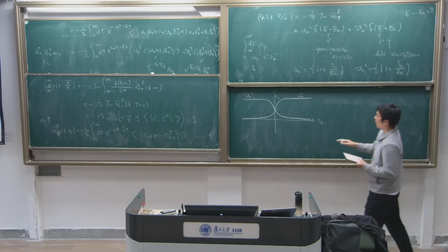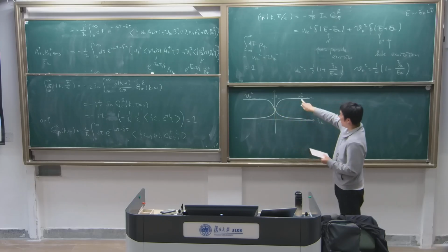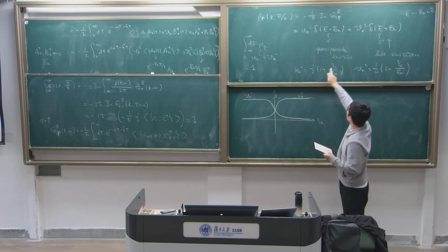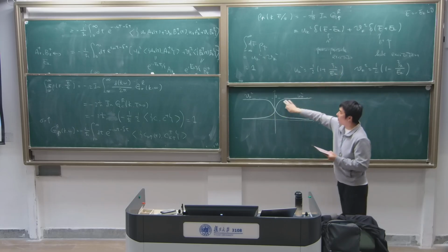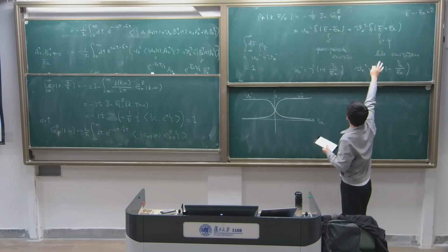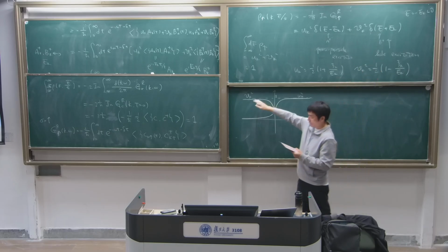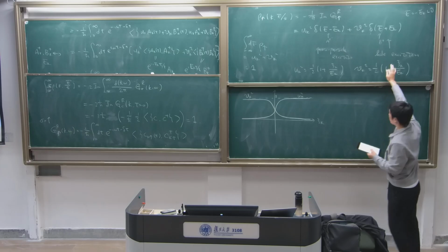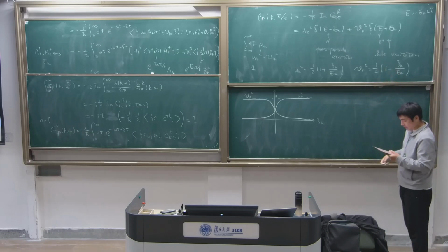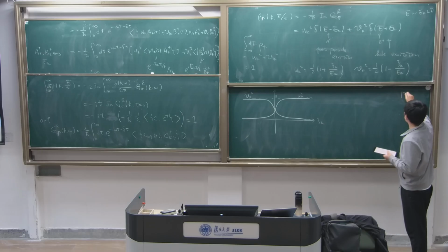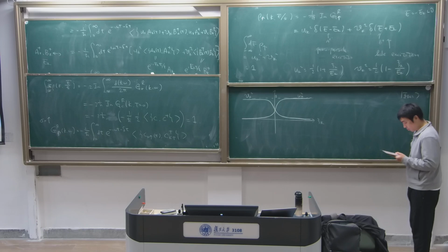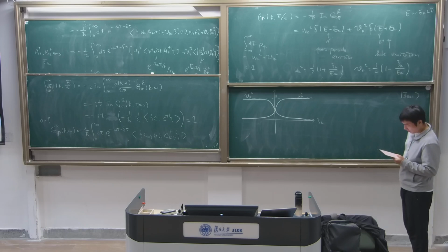So if you have xi_k positive, the weight to the positive particle excitation is dominant. So this is a weight u_k is dominant. Whereas if xi_k is negative, you have hole excitation. You just get rid of some states from the BCS component space. This is the BCS state. You just get rid of some states from it. So that is the problem.